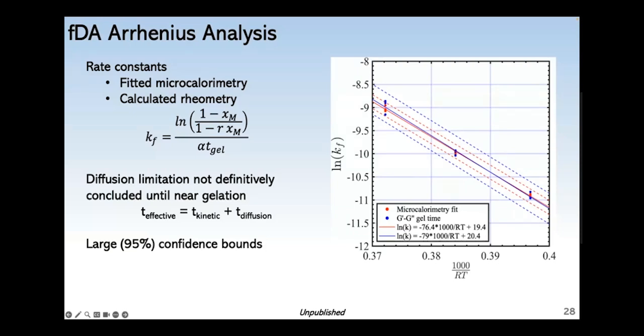And the fits agreed better than I would have expected by just plugging in the gel time, because I would have thought the rate constants with the gel times would have been leaning more towards the diffusion regime. But I didn't really see that with the forward analysis here. But then again, I have fairly large confidence bounds on my fits, which is the dashed lines, which intersect for the two data sets.